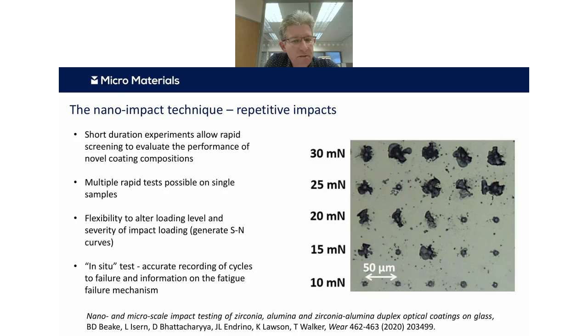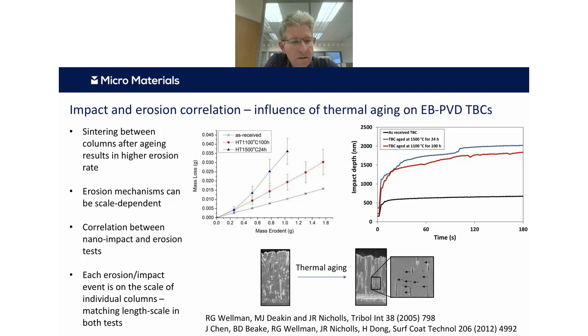And each of these tests, as well as the microscopy that you can see on the right, also has all of the depth versus time data and the number of impacts to failure data associated with that. So you can build up these very accurate pictures of time to failure. So as I said, it correlates very nicely typically with erosion testing.